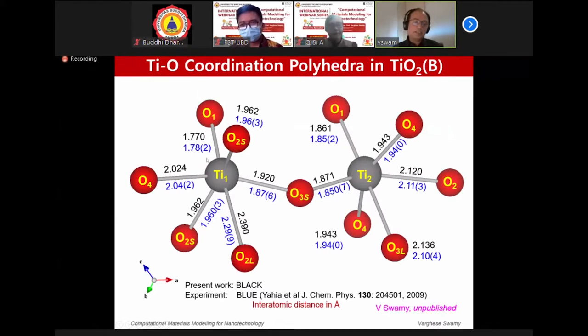And the bond lengths are calculated very close to what's obtained experimentally and using some other ab initio calculation. So it's highly predictive. Now we can rely on this calculation to tell us what might happen if I do a computational experiment by taking this material through high pressure.